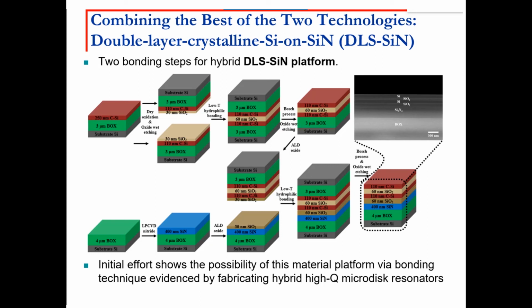In order to marry the two technologies I showed you, we need something that has double layer silicon in order to minimize the power consumption over silicon nitride. So the same technology, but rather than using one layer of silicon, I use 2 layers of silicon as a capacitor to do that. And of course, we have developed this bonding technology. This is the SEM of the bonded material. So now we are working on making devices in it.